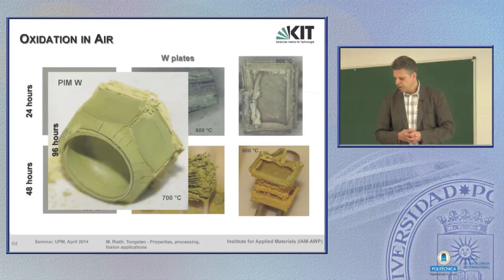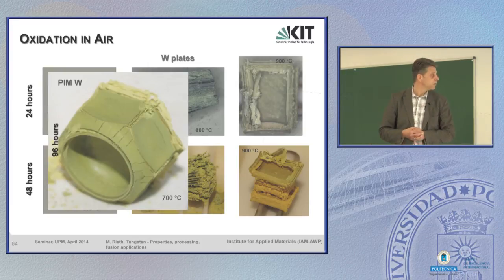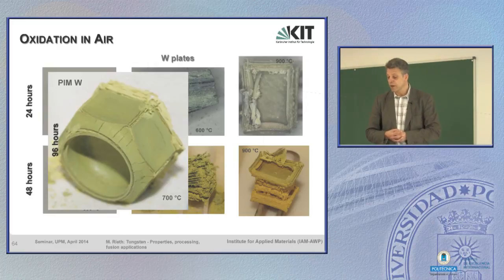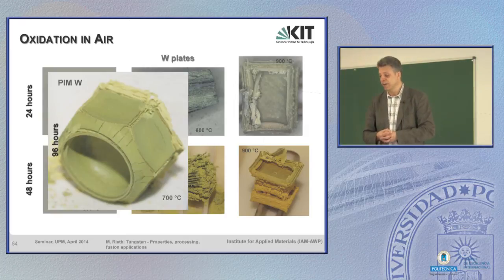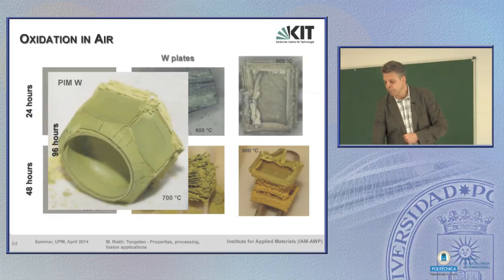What I want to mention very quickly, because you see it very clearly here, is that oxidation in air is very problematic for tungsten. At 500 C, nothing happens, only the surface blackens a bit, but then it stays that way for years. But at 600 C, you see what happens to the plate.